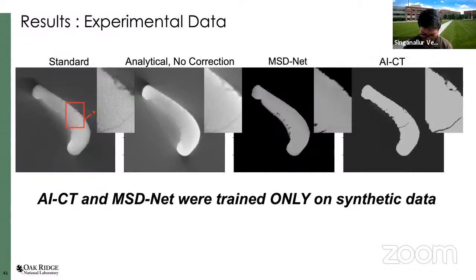And then we, of course, applied it to some real data. This is what we see, a real jet engine turbine blade that we scanned. We used the networks that we trained purely from these CAD models. This is the analytic FDK method, which is fast. And then this is the net outputs from the neural network. Now you can see that it clearly clips, or rather forces the value to be positive. That's because of the nature of the CAD model training. But in this case, we can see this crack that we think is pretty nicely reconstructed, but we still have some ways to go, right?